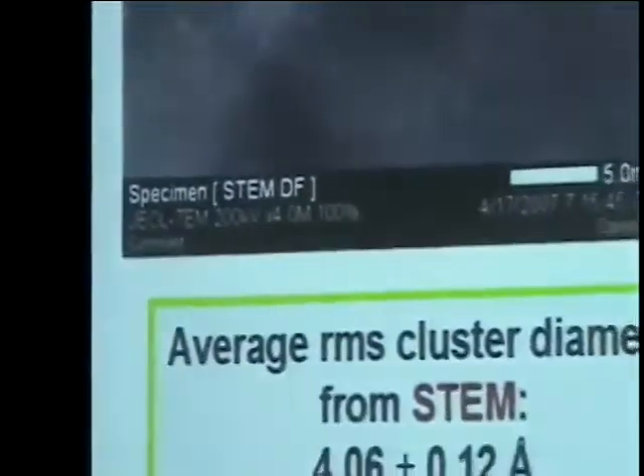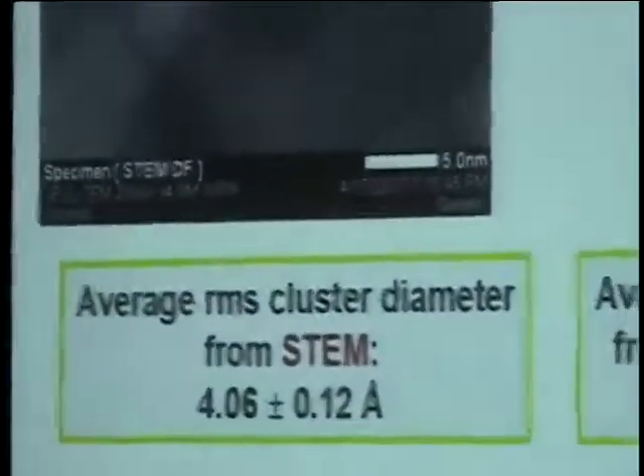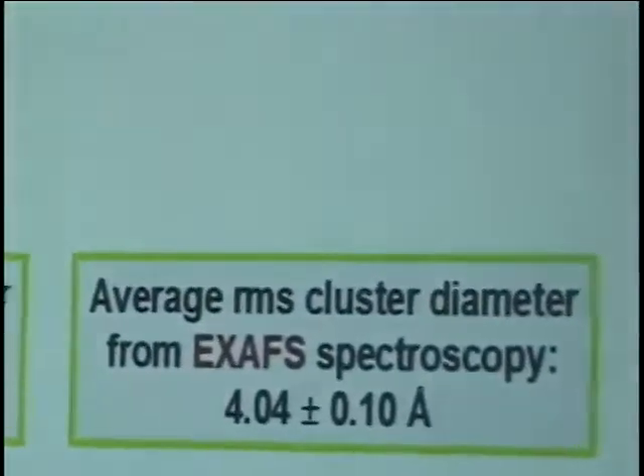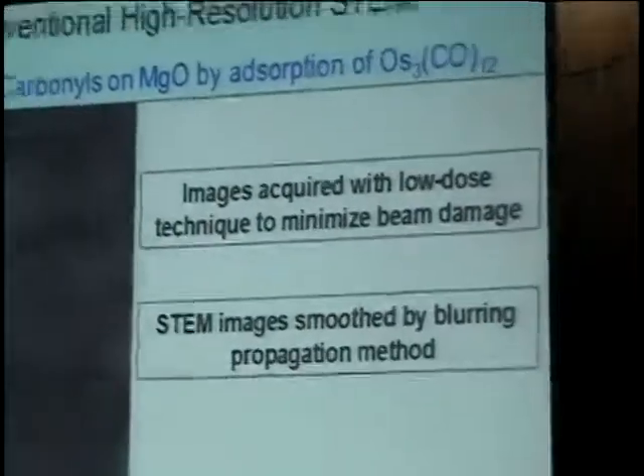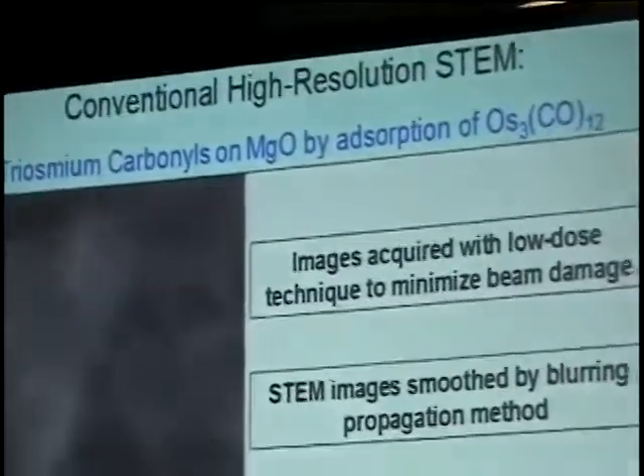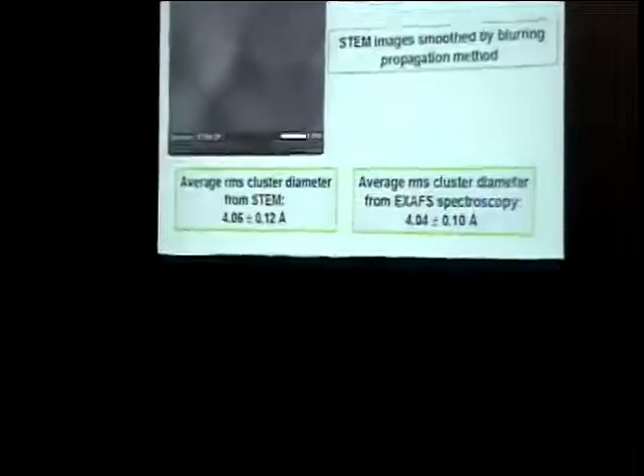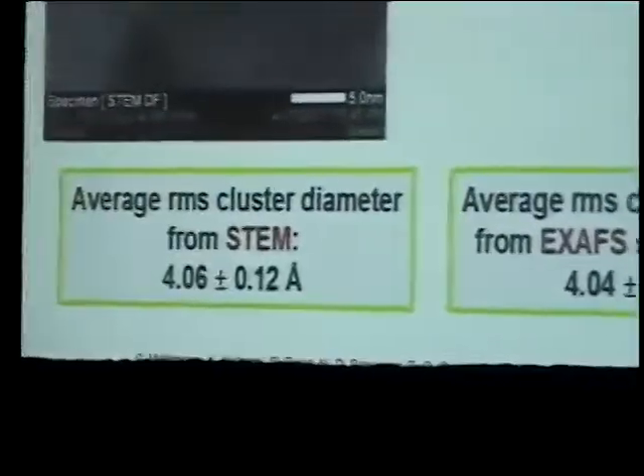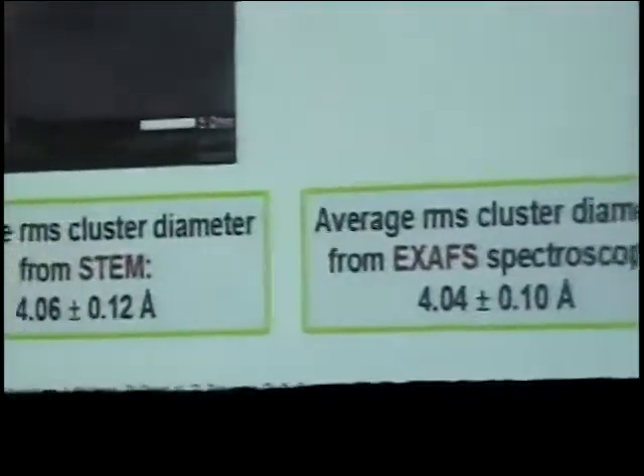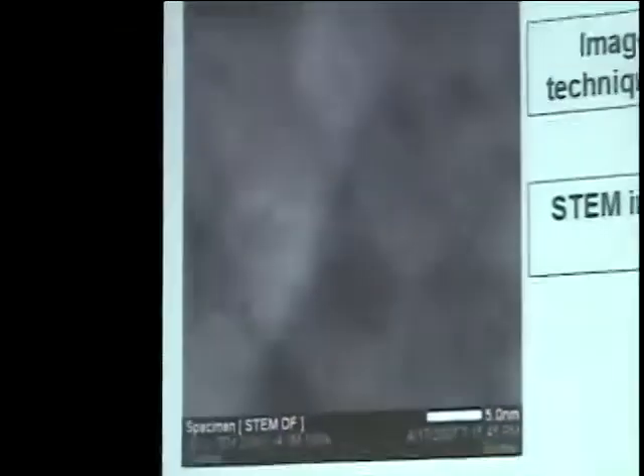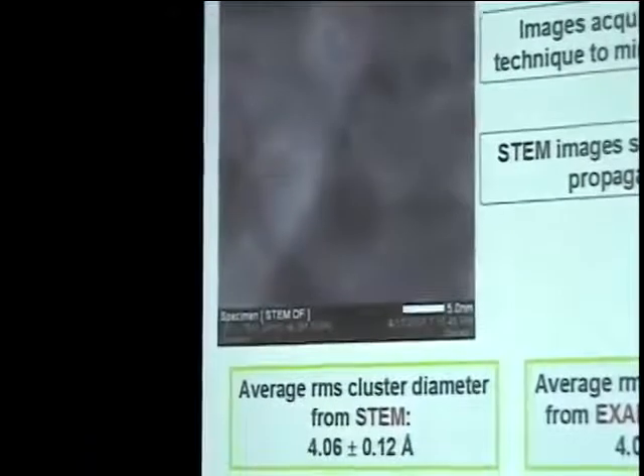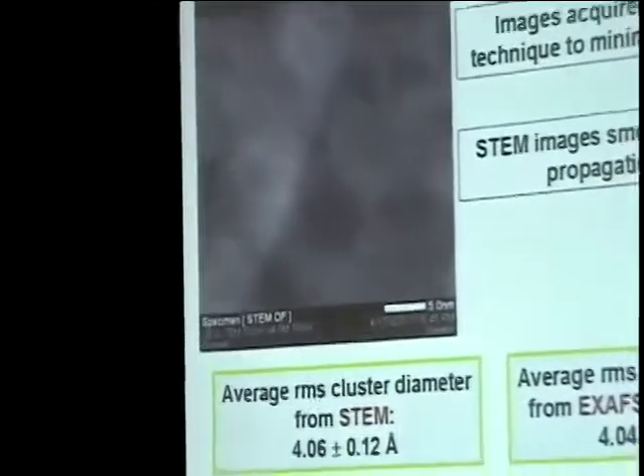Okay, so let's go back. You can't see the bottom, it's cut off a little bit. But a few years ago, we did some conventional high-resolution electron microscopy, scanning transmission electron microscopy, characterized what we made by adsorbing the triosmium clusters on MgO. And I'll come to the details of that, but the cluster frame remains intact. And the evidence for that is, we look at the images, and this is not impressive by today's standards, but it's analyzable, and maybe with this light you can't see too much, but there are clusters discernible there.